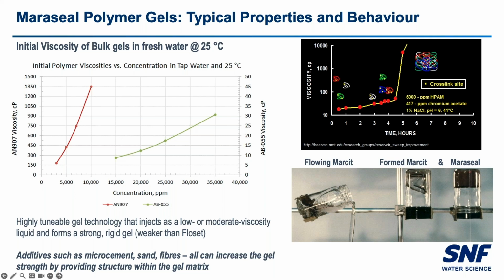And we can modify the chromium content to change the gel structure. We can also increase the strength, and this is what we're working on right now, looking at additives, microcements, sands, fibers, and this might only need to be added to the very last volume that's injected. So the previous gel injected may be strong enough, and then we just cap it above the perforations with something that's a little more rigid with some sand structure. In the top right, though, you see this particular polymer system. Excuse me.